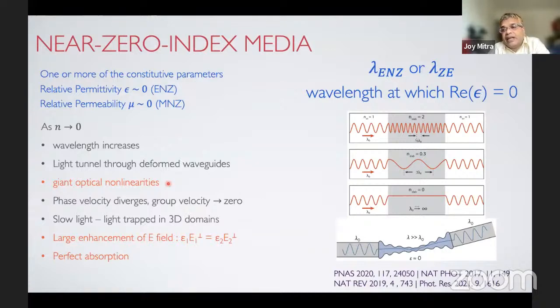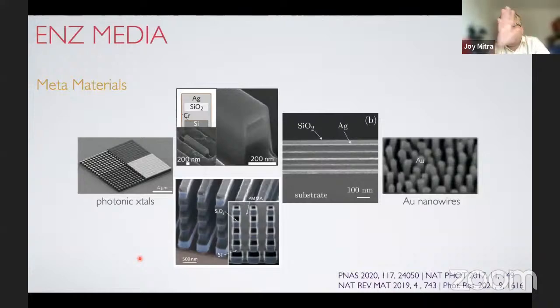You get a large electric field enhancement within the epsilon near zero media, simply because the boundary condition dictates it to be so. If one of them is a normal media, the other is where the epsilon goes to zero, naturally the corresponding electric field to preserve the boundary condition blows up. And it has very important consequences in perfect absorption, tailoring emissivity, rather a fascinating journey, which we have recently started in the lab. Okay, much of the epsilon near zero research has essentially been in the past on very sophisticated and rather complicated structures like photonic crystals, metal semiconductor waveguides, multi-stack layers of dielectrics and metals, metal nanowires stacked and oriented. And it has been rather nice to see all these exotic structures.